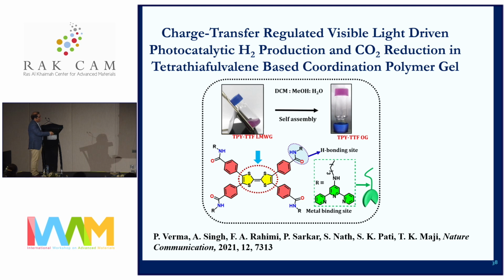To understand whether a redox active ruthenium or any redox active molecule has a role, here we took the zinc site, which has a D10 electronic configuration. In the previous case, ruthenium can become ruthenium-1, which has significant impact during catalysis because it can directly accept the photogenerated electron. But zinc, with its D10 electronic configuration, is redox inactive.